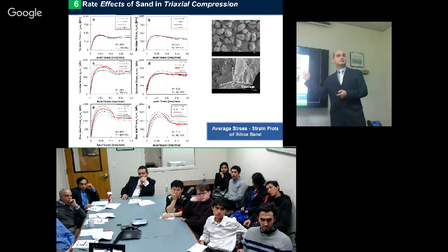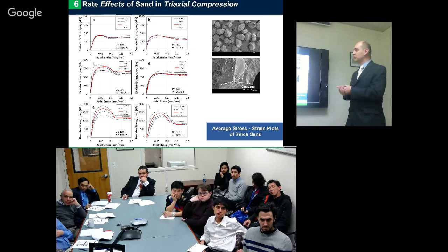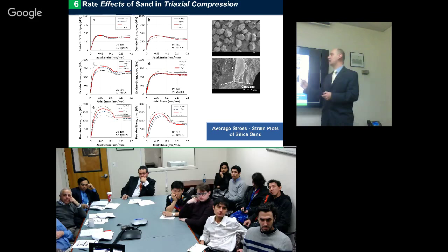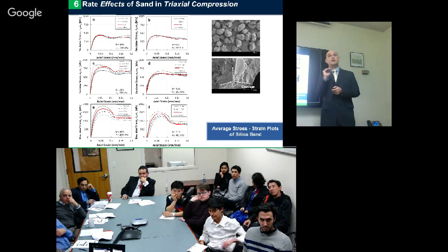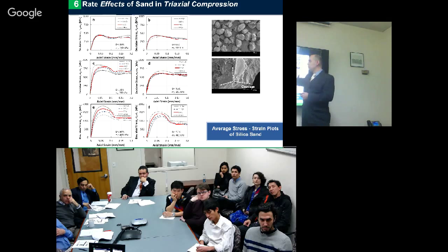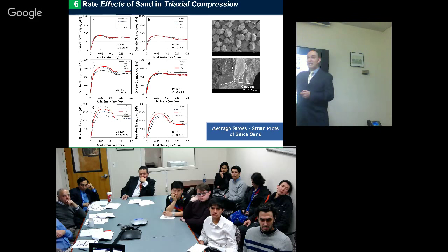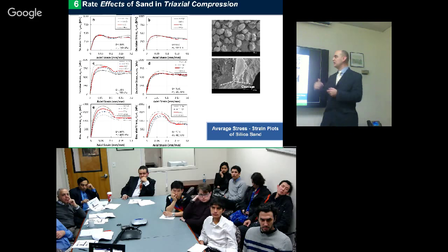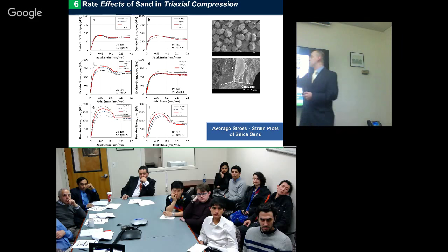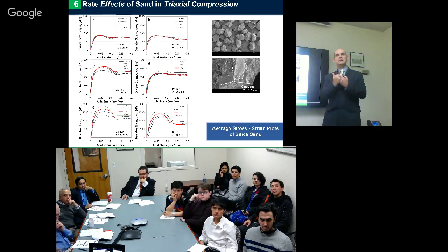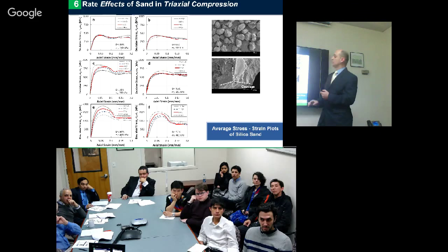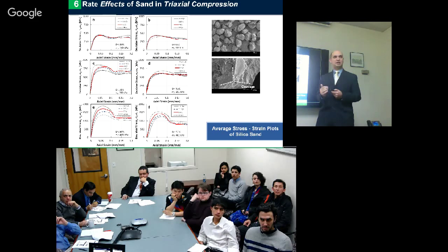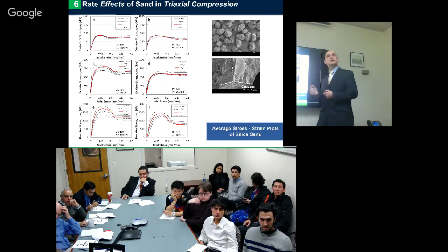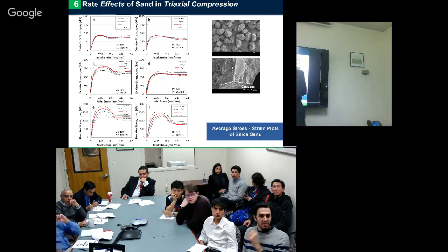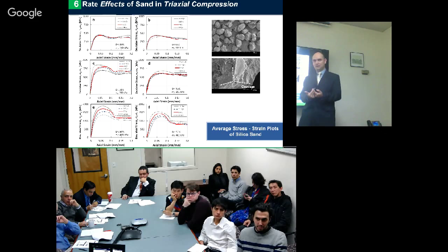Now, these are the averages, the plot of stress-strain behavior. Remember that we have 3 main confining stress conditions: 100 kPa, which is the first row, 200 and 400 kPa. And on the left column, we have a very dense material, 85%, and on the right side we have 55%. So this is dense and this is loose. The different colors and different types of lines represent different strain rate conditions, from 0.01 up to 10% per second. Here we see a negligible effect of strain rate.